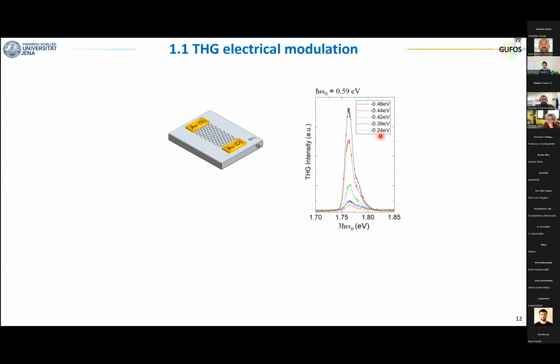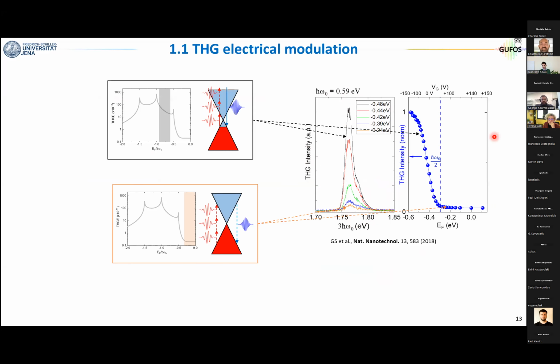And you see that by changing the Fermi energy, we have a very strong change in the third harmonic intensity, that is our y-axis. And in order to make this graph a bit easier to read, I now take each of these curves, calculate the total intensity, and plot it on this graph now on the right, where we have on the top x-axis the gate voltage, the bottom is the Fermi energy, and on the y-axis we have the third harmonic intensity.